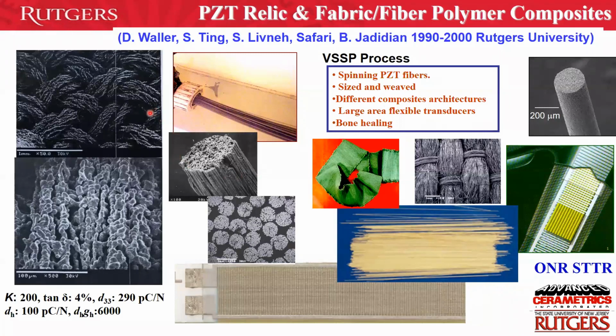First we started making this by the relic process, taking a fabric, which could be a carbon fabric or cotton fabric, and then immersing it in the sol-gel solution of the PZT. After careful drying, we impregnated it with the polymer and made a composite. This is really fine scale, and the properties were great.